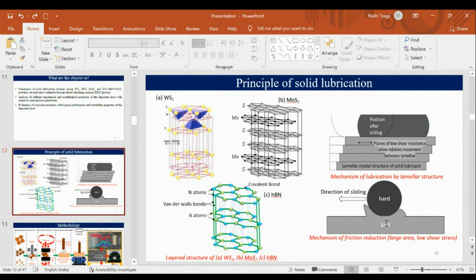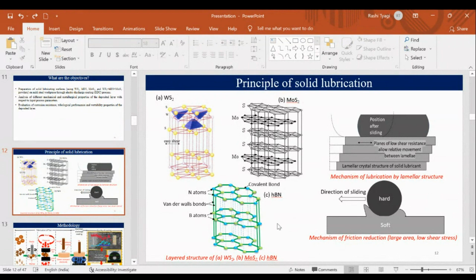In a tribological test, you use two surfaces. First is the counter disc, and second is the pin or coating that you are using. Imagine this is the coating and this is the pin; if it is soft, then it will align itself in the direction of motion. Then a large surface comes in contact with the hard surface, so shear stress will be low. Why? Because shear stress is force per unit area. It means force applied per unit area. So if the area is high, then the shear stress will be low. That low shear stress helps in providing a low friction coefficient. So these are the properties of solid lubricant that we will utilize in this work.